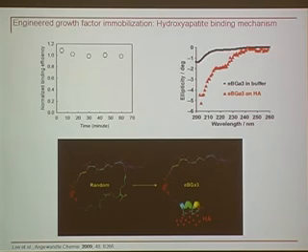So the suggestion here is that in the presence of hydroxyapatite, the binding between the peptide and the surface is stabilizing an alpha helix. Random coil in solution, when bound, we see this helix forming. And importantly, this is what happens in osteocalcin. So we think we're mimicking the structural transition that happens when osteocalcin binds to a hydroxyapatite surface.